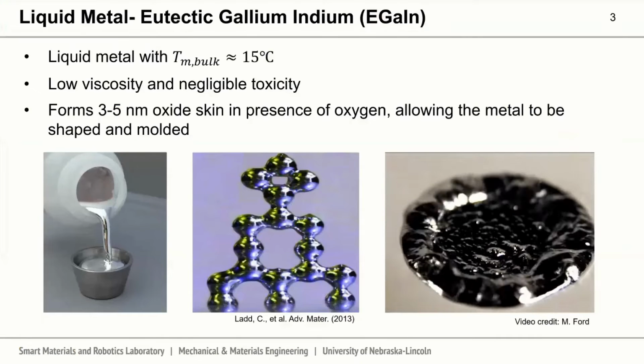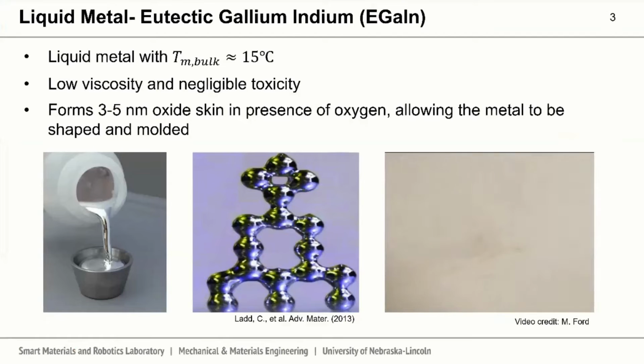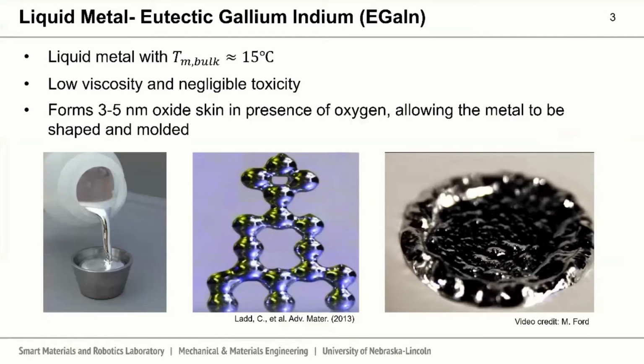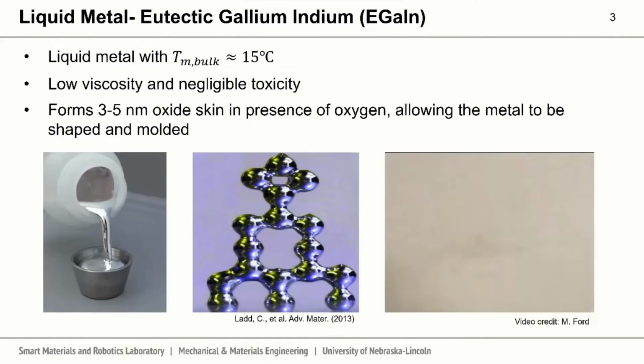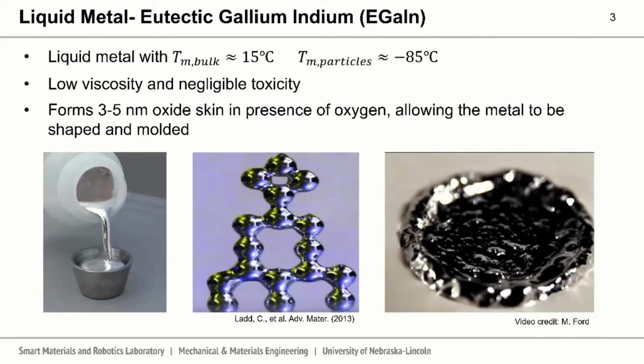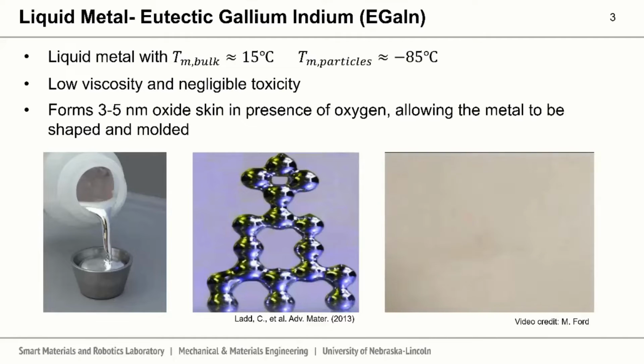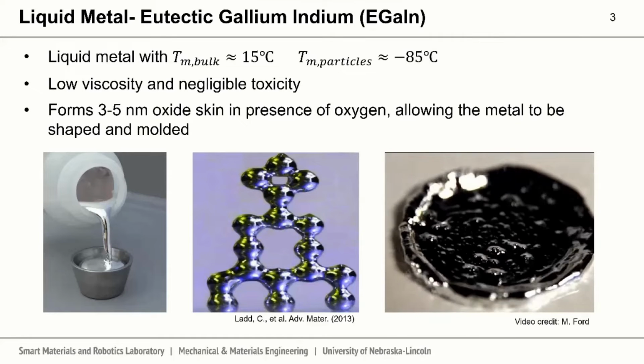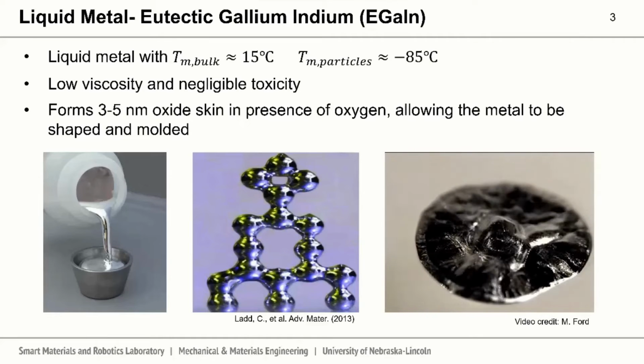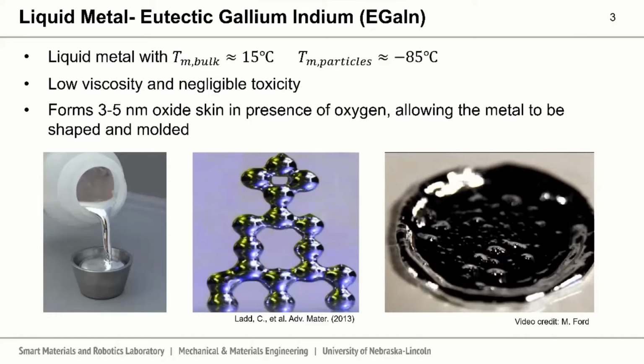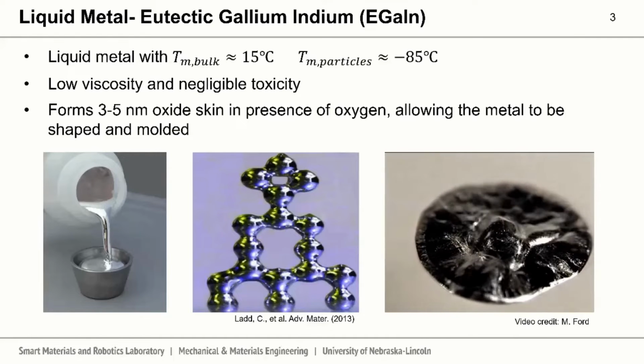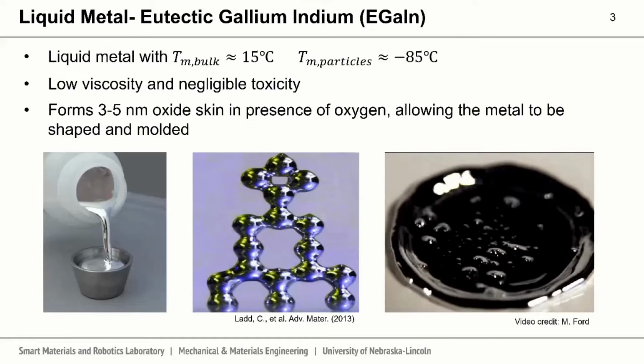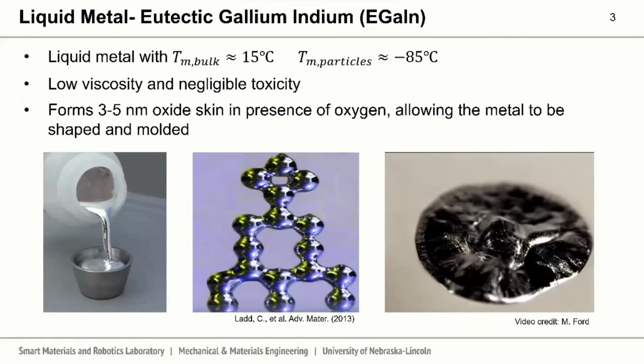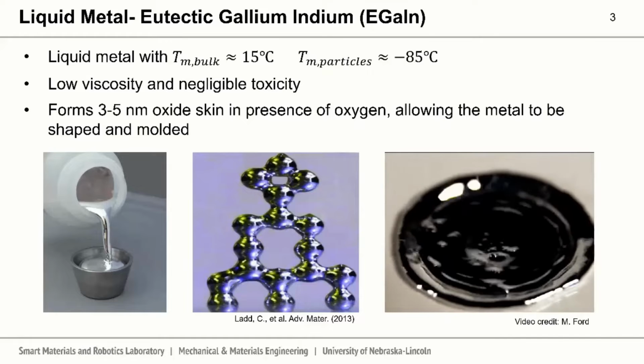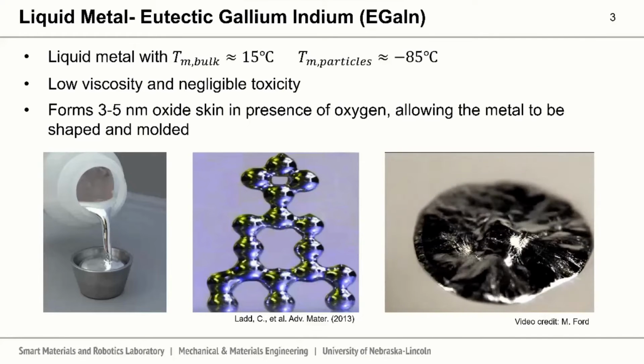So today I'll be talking about liquid metal composites, specifically eutectic gallium indium. This is a room temperature liquid metal where the bulk melting point is around 15 degrees Celsius. When it's broken up into particles or droplets, this melting temperature is suppressed all the way down to negative 85 Celsius. The metal has a very low viscosity and negligible toxicity. One of the really unique properties of this liquid metal is it forms a very thin oxide skin in the presence of oxygen, about 3 to 5 nanometers in thickness, which ultimately allows the metal to be molded and shaped.